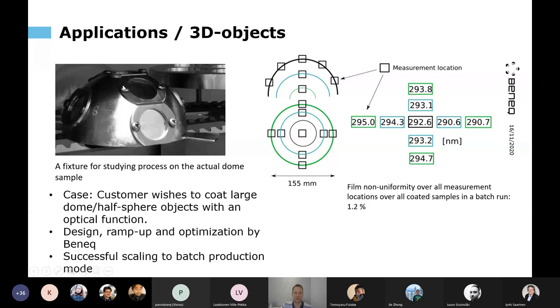So what we did is this dummy jig that we can mount smaller samples on and use this for process optimization, measuring the thickness on these flat samples. Then after tuning the process, we can use that to coat the actual parts. So that's a typical way we sometimes need to work with these complex shape objects. In this case, also the uniformity over the batch, actually there were several such objects, we found 1.2% non-uniformity, so that's sufficient for this kind of application.